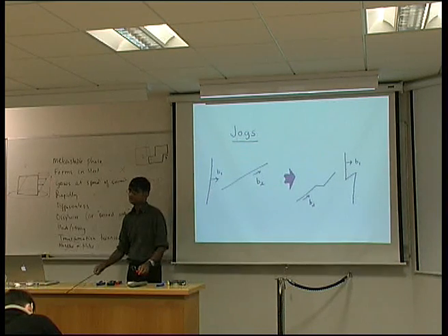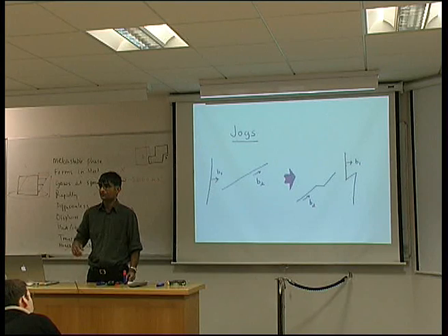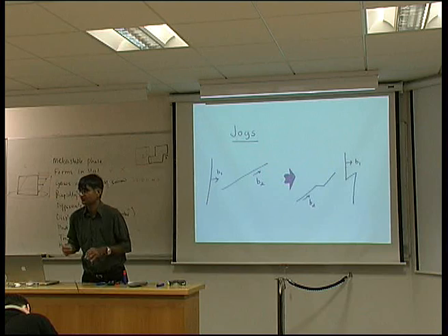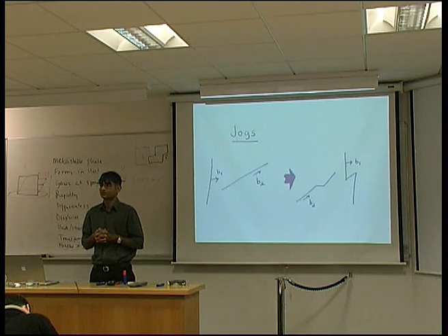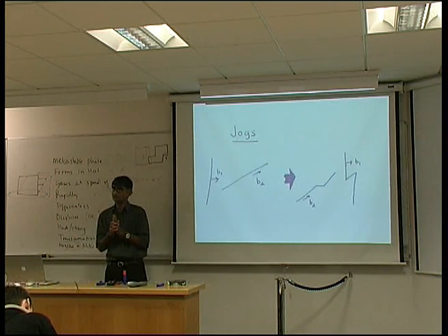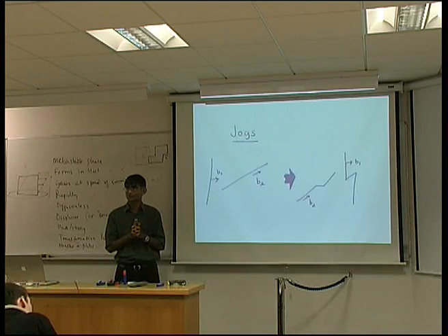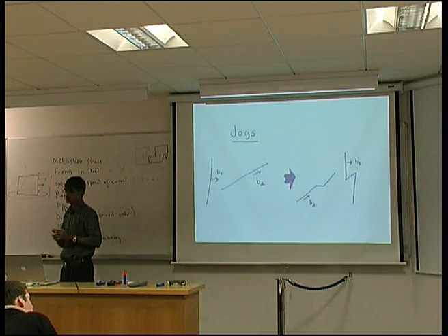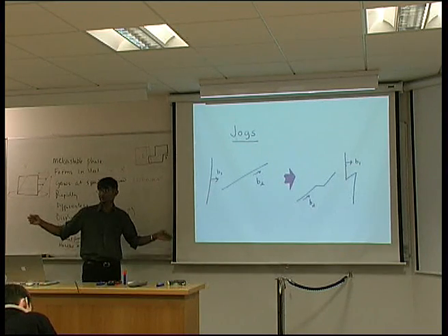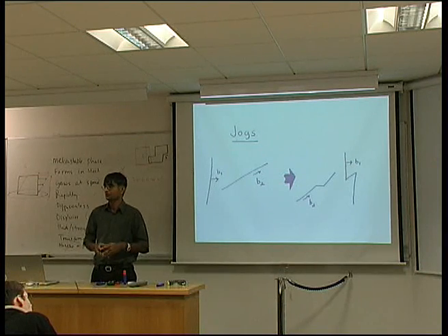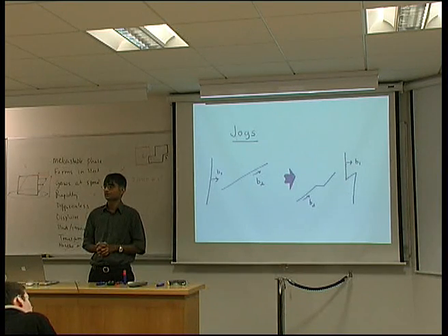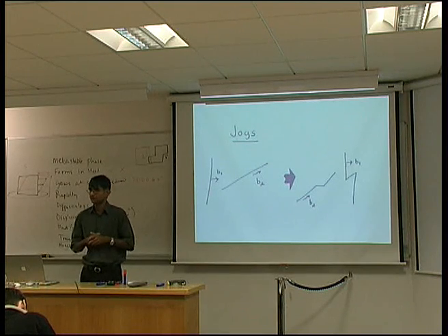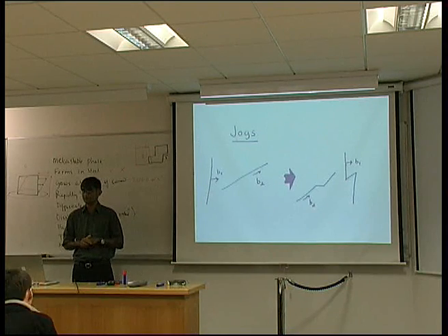So intersecting dislocations are troublesome. They can render the interface sessile, because they introduce these jogs. And that's the reason why we can only tolerate one set of dislocations in the interface between martensite and austenite. And those dislocations must lie along a perfectly coherent line in the interface. Everyone happy with this? I know you haven't done jogs before, but it's fairly clear, isn't it? Shout if you don't understand, alright?